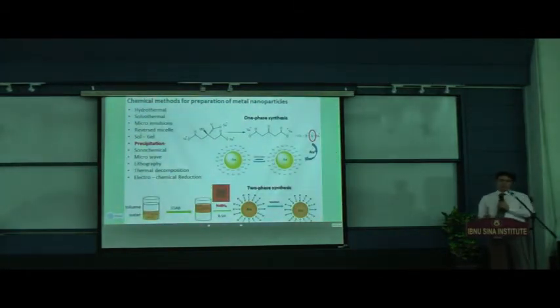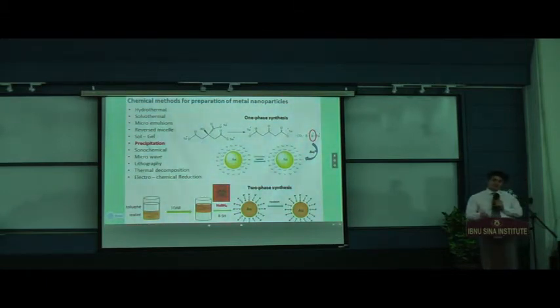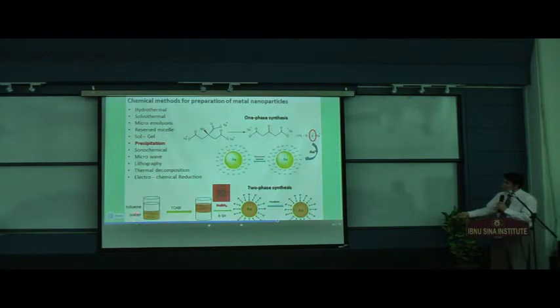And as I mentioned earlier, there are two main ways to synthesize metal nanoparticles, especially noble metal nanoparticles. One-phase synthesis, which is citrate chemistry. Citrate is used as reducing agent and stabilizing agent. And the second one is two-phase synthesis, or the Schiffrin method or Brust-Schiffrin method, which is useful to put organic materials at the surface of nanoparticles, because some organic compounds are not soluble in water. This is water-based synthesis. But this is two-phase, water and toluene.